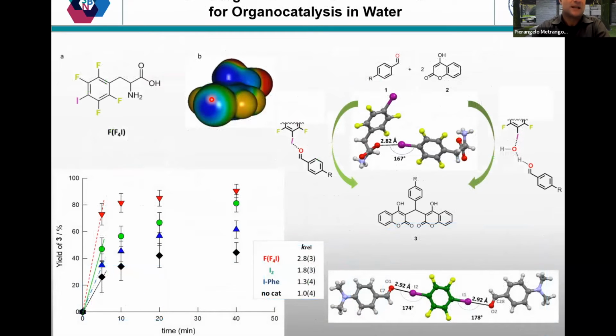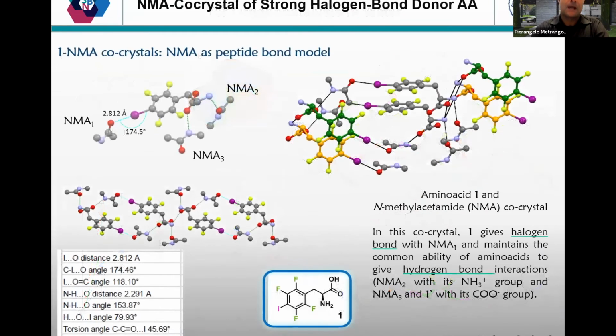So obviously now this iodo-tetrafluorophenylalanine is a very strong halogen bond donor. It is soluble in water. You can do organocatalysis in this kind of condensation reaction, where you can see that this small amino acid is making halogen bonds with itself and the substrate. So we also crystallized this amino acid with N-methylacetamide, and we discovered that this halogen bond donor makes very strong halogen bonds, as you can see, a 20% reduction of the sum of the van der Waals radii.